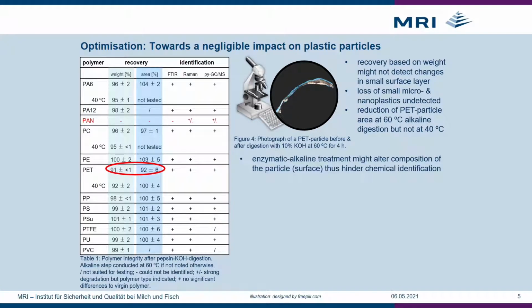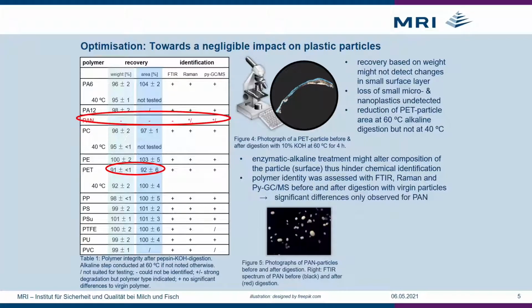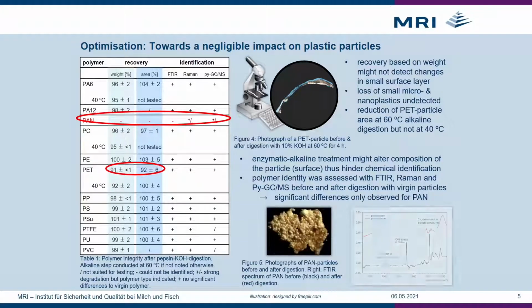Aside from polymer loss, the chemical composition of the particles might be altered by enzymatic alkaline treatment. So we assessed polymer identity of virgin plastic particles with FTIR, Raman, and pyrolysis GCMS before and after application of our digestion protocol. Significant differences in the chemical composition were only observed for polyacrylonitrile, though.